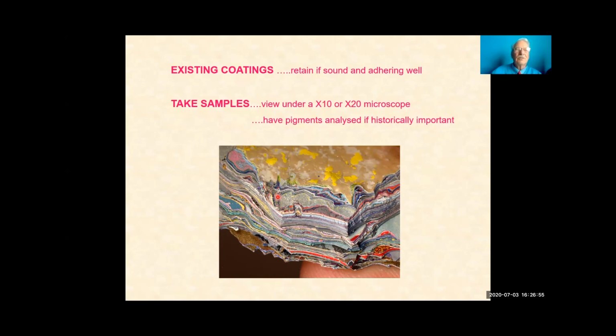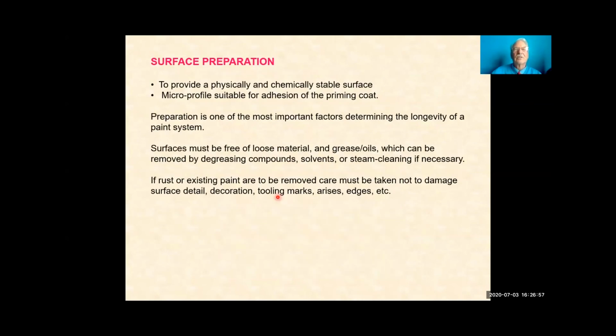So we've obviously got to prepare our surface before we put any paint on. That is to provide a physically and chemically stable surface and a micro profile. It means roughness suitable for the paint to adhere. Remember, a paint will eventually fail by falling off. So you want to get the surface clean and you must have it rough so that the paint can hold on to it. It's the most important factor in determining the life of the paint.